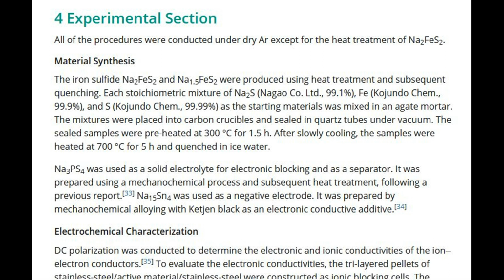The mixtures were placed into carbon crucibles and sealed in quartz tubes under vacuum. The sealed samples were preheated at 300 degrees C for 1.5 h. After slowly cooling, the samples were heated at 700 degrees C for 5 h and quenched in ice water.